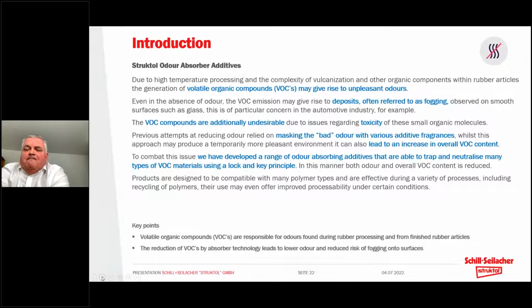So odor absorber additives: we really want to remove some of the malodors that are generated during processing and post-vulcanization from a variety of organic components that we find within rubber articles. We know that these VOCs, these volatile small molecules, can give rise to unpleasant odors. Even in the absence of malodors, we see unwanted effects such as fogging, the deposition of these fuming materials onto surfaces such as glass. For example, in the automotive industry, fogging is often discussed in terms of the deposition of all kinds of volatile materials found in the cockpit. And of course, the VOC components in a great number of instances can be considered quite toxic, depending on the type of VOCs that we face in the polymer industry.